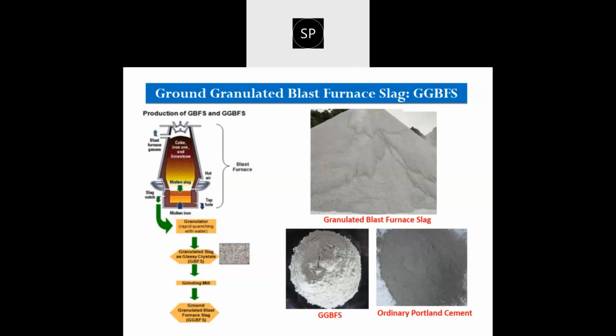Due to this particular process, glassy content develops inside the granulated blast furnace slag, and this glassy content is normally between 85 to 90% as per the IS standard, for its utilization as a replacement of cement in pavement quality concrete. If the glass content is less than 85%, then this sort of material will not have the requisite hydraulic and cementitious properties, and therefore all cement manufacturing companies reject the GBFS which has a glass content less than 85%.